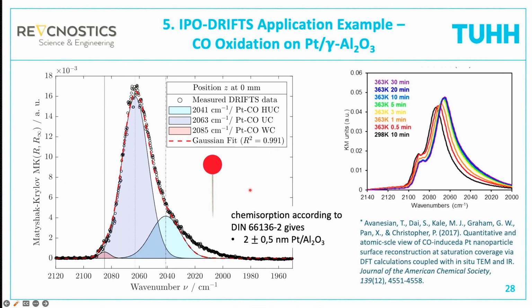And when we do now the double difference calculation, then you see we get very nice signals of adsorbed CO. And we can even distinguish what molecules sit where. So we see that we have very few CO molecules sitting on well-coordinated sites. And this is no surprise because our particles were only 2 nanometers, as we determined by chemisorption. But the majority of molecules sit on under-coordinated or highly under-coordinated sites, as we have in corners and steps. Okay, so this is all in line with what you expect also from literature.